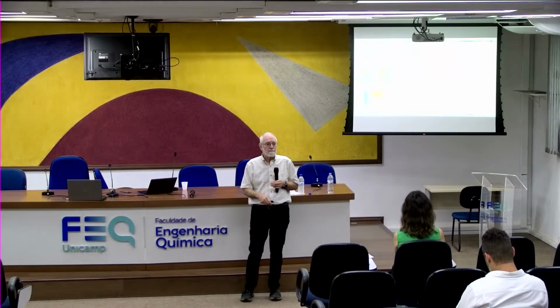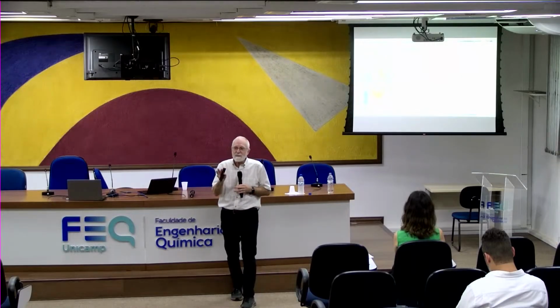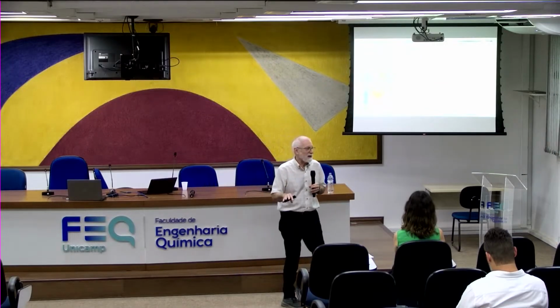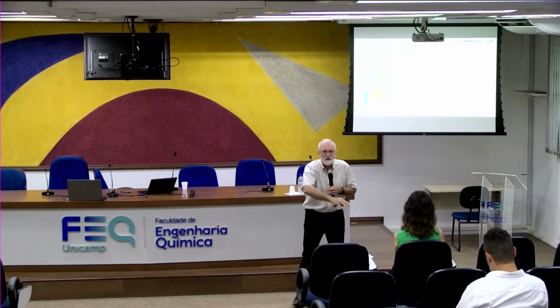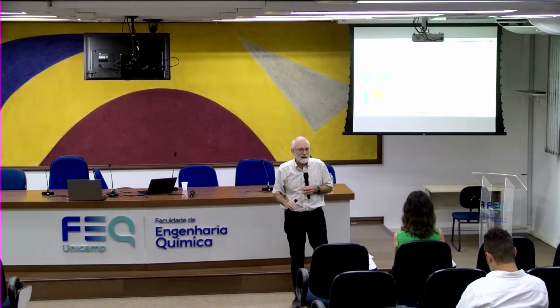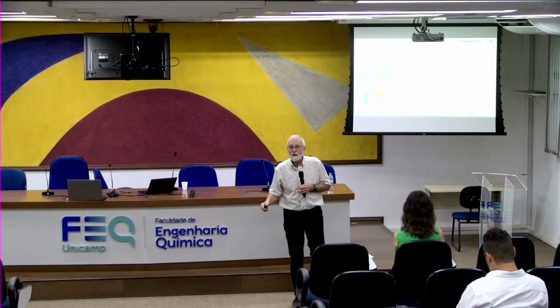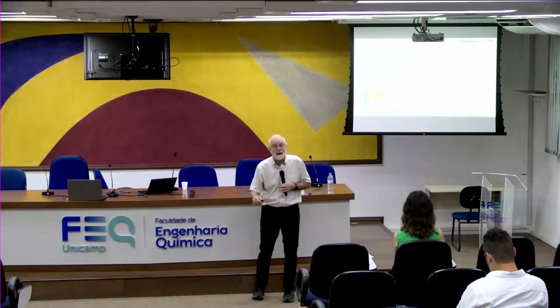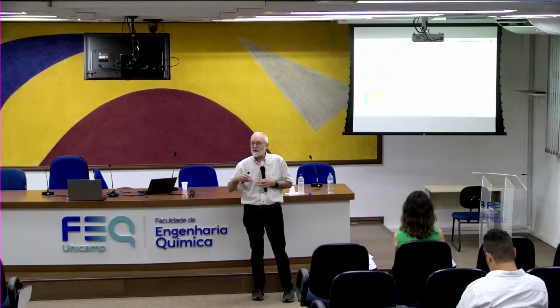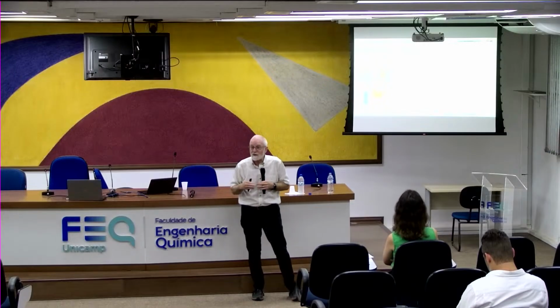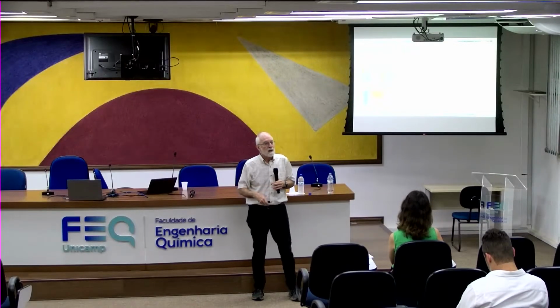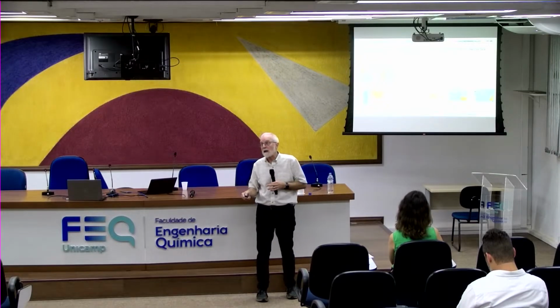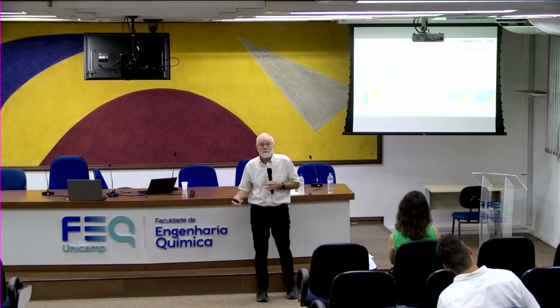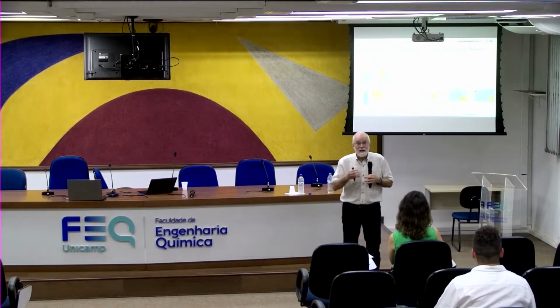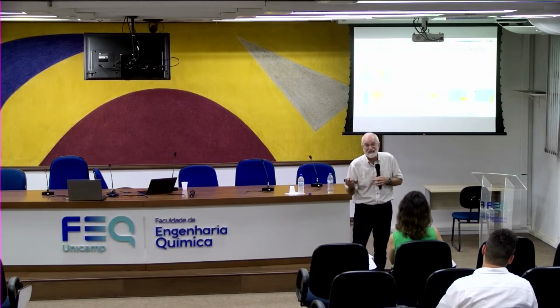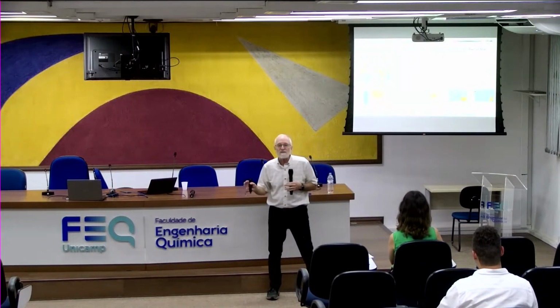They behave like silicones. There's some other advantages. Anybody who's ever been in production in a company knows you make bad batches, right? Here's the design, here are the reagents, we made it for the last year exactly the same way, and today we get a bad result. What do? Landfill it. No. In this case, because those sulfur-sulfur bonds are dynamic, we can add in a new silicone with a different chain length and either increase or decrease the cross-link density. You just heat it up and cool it down. But the real advantage is now we can take a silicone elastomer and reduce it all the way back to a monomer under mild conditions, which again is attractive. We can make silicone lipoic acid materials that are 60, 70% lipoic acid, but we can get rid of them at the end of the day.